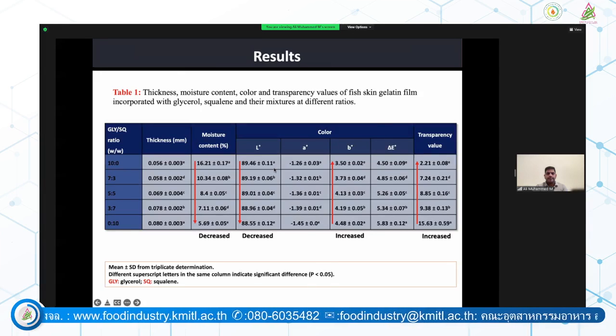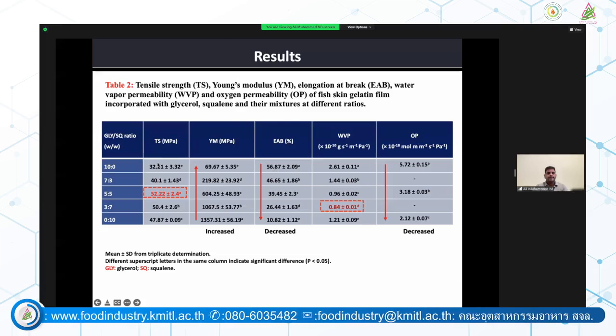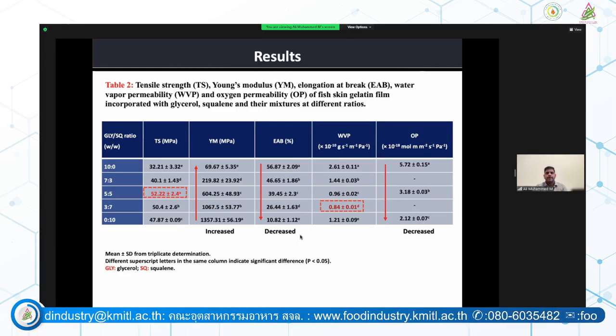So these are the basic parameters tested, and we can see this addition of squalene could increase the tensile strength of the film. We saw the replacement of glycerol with squalene at a 5:5 ratio yielded the highest tensile strength. But we saw that Young's modulus increased as glycerol was replaced with squalene, and even elongation at break reduced with the addition of emulsion.